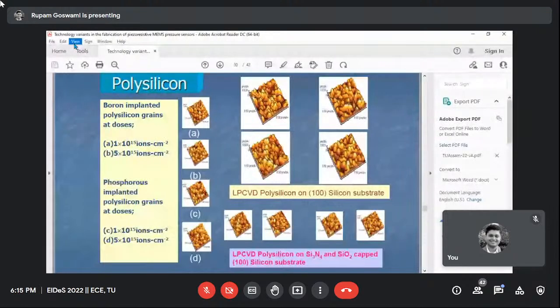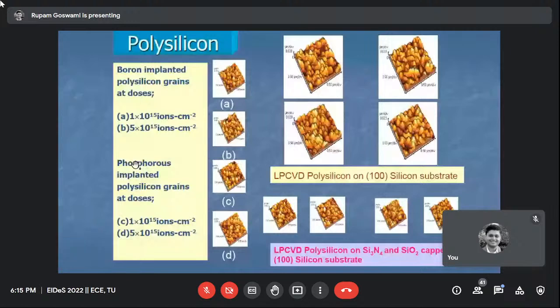So actually, the purpose of mentioning this is that polysilicon plays a very important role in piezo-resistive pressure sensor fabrication, in one type of version that I mentioned earlier. We can tune the properties of the polysilicon, including its piezo-resistive coefficients, by controlling the grain growth at different temperatures, and the grain size. We can also study where it will give more stable performance. This is the window where we can tune the properties of the final pressure sensor, so how the technology is going to bring a change in the performance of the pressure sensor.